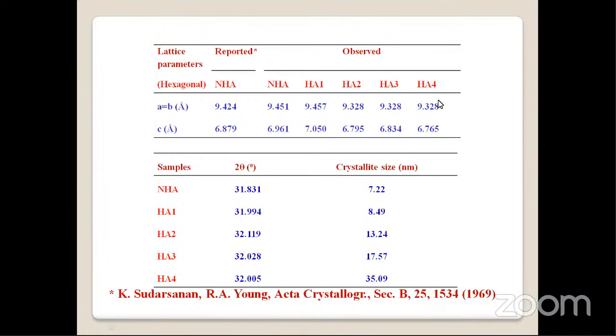But in our experiments, we recorded these a, b, c values for all the temperatures, and there are not many variations. It also confirms that there is no structural variation. The structure is very, very important, and we are discussing it at the angstrom level. If you take it to the nano level, 9.4 angstrom becomes 0.94 nanometer. It is very important that we are discussing in the nanoscale. That is why nano is very, very important.